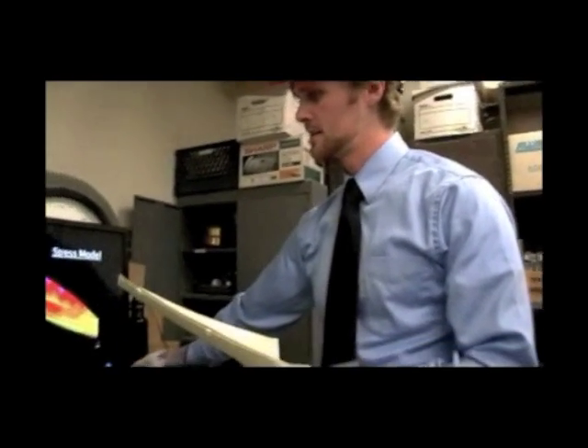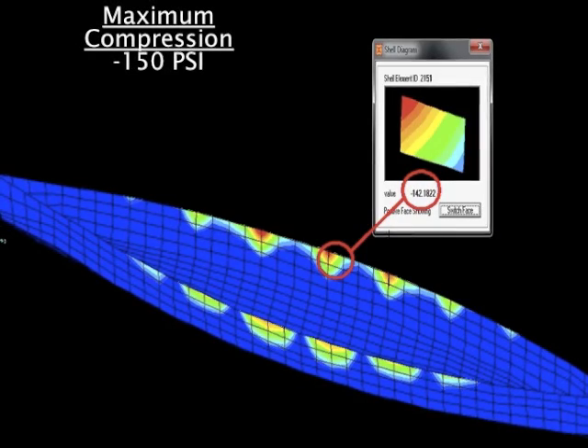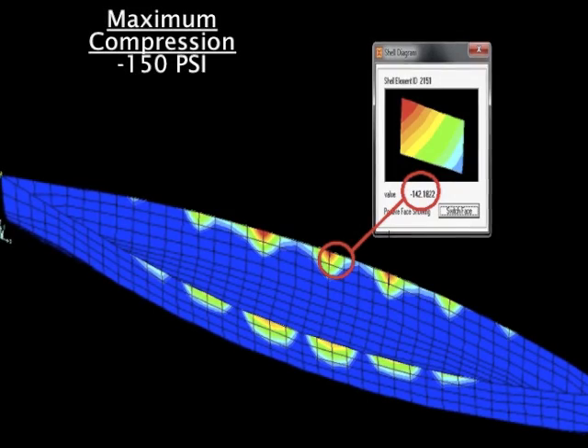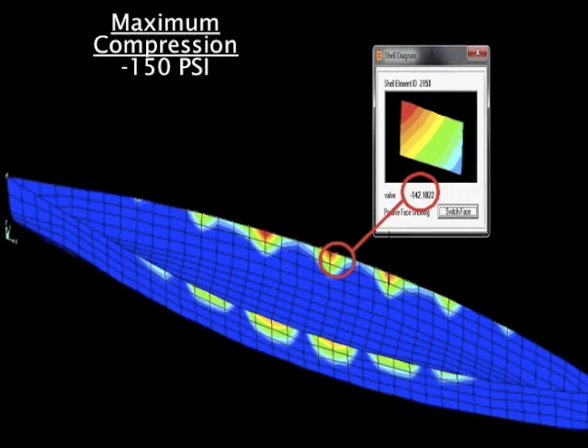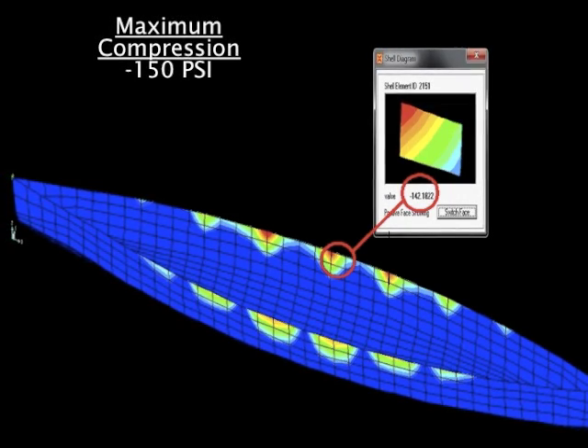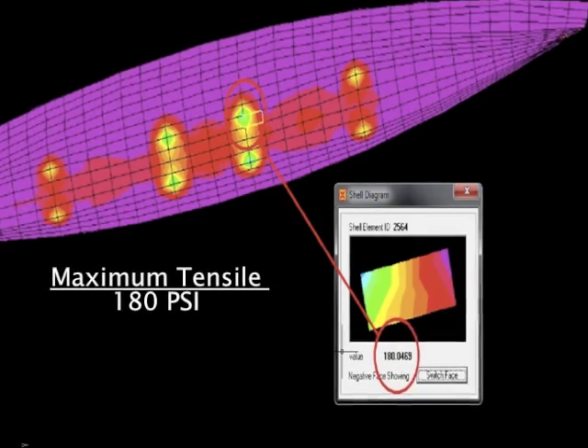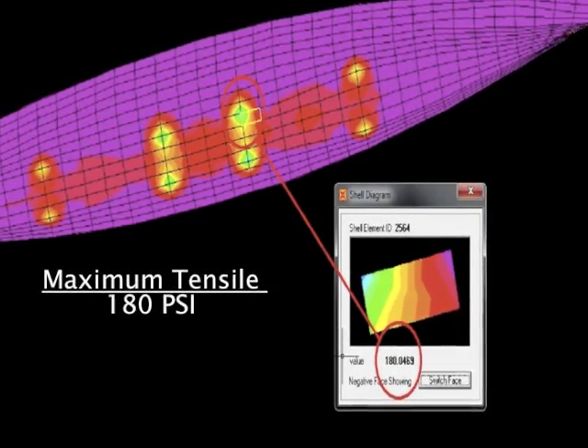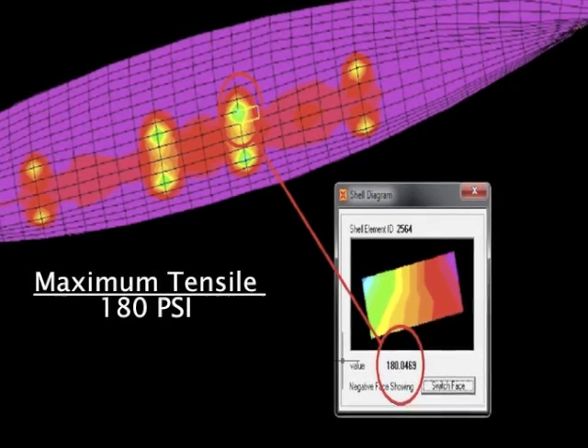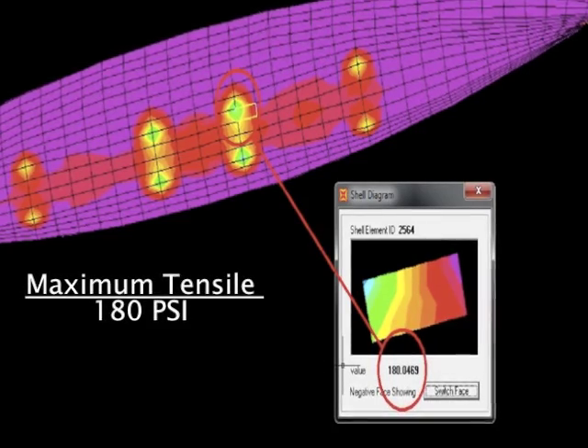When doing our analysis on the canoe, we took the heaviest loading, which was the 640-pound load with 2 females and 2 males, the 4-person slalom, and we modeled that in SAP. The maximum compressive stress you can see is located on the rails. The rails is where it really crunches up when we had the applied load in the middle of the boat. The tensile maximum point was located on the bottom of the boat, where the heaviest paddler in the middle was.